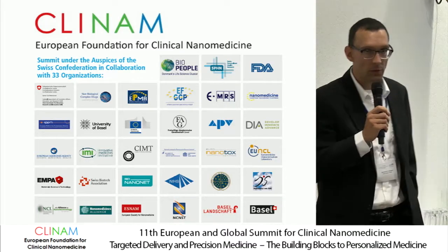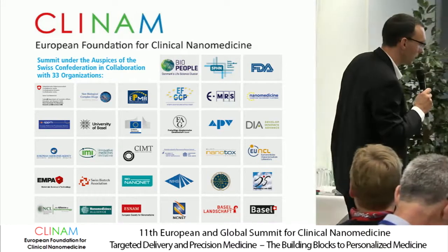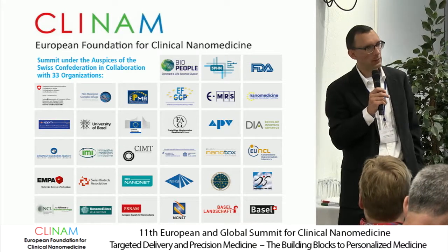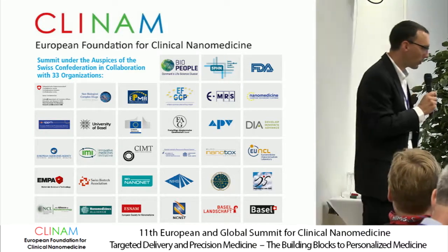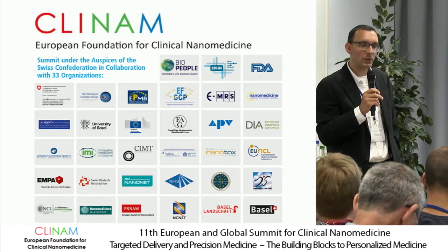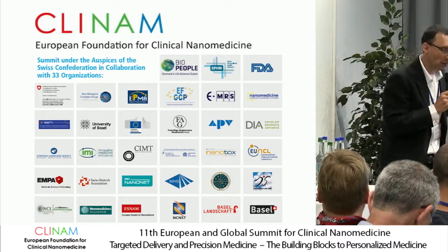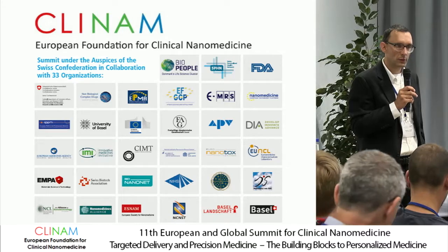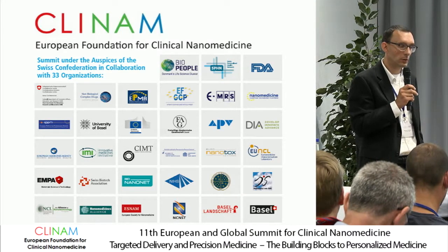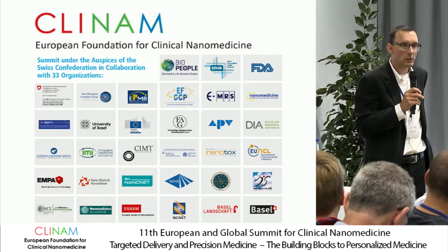Basically, whenever you do concentration, it's key that you calibrate, and we don't make a fuss out of it. It is very important to calibrate, and once you measure gold, it's a different calibrator rather than polystyrene. It's based on refractive index, and this is key. If it comes to complex mixtures, we can scale with intensity. So we have the scatter plots. So we know the individual subpopulations, and we can really see the differences.